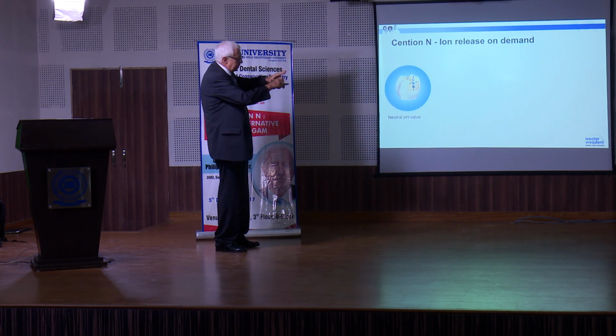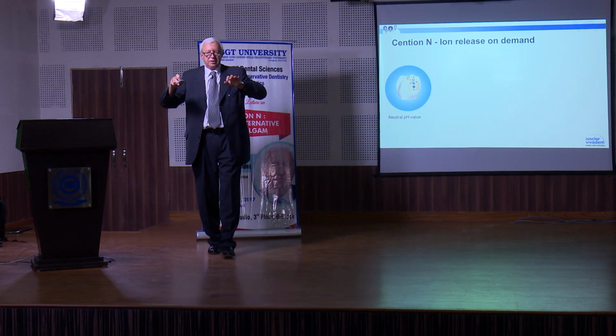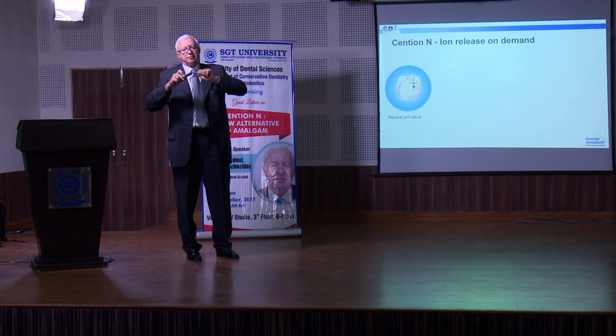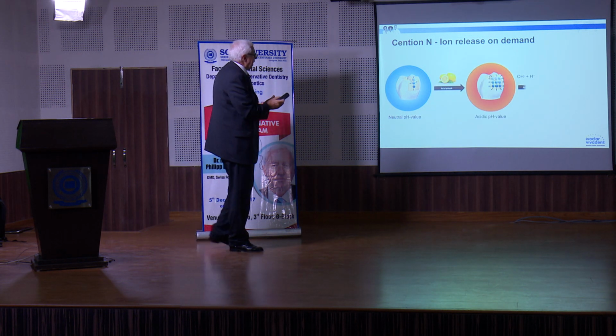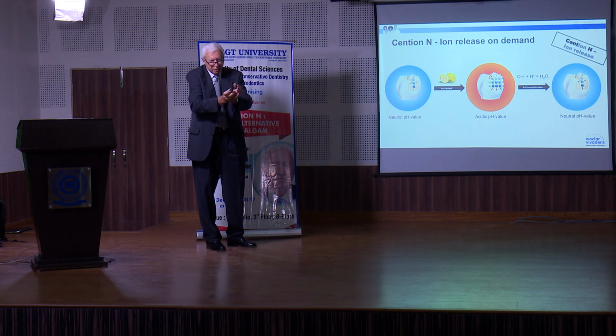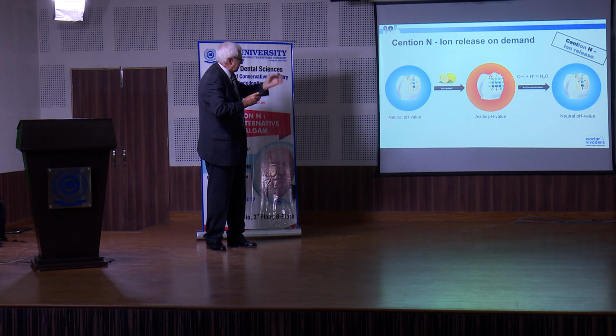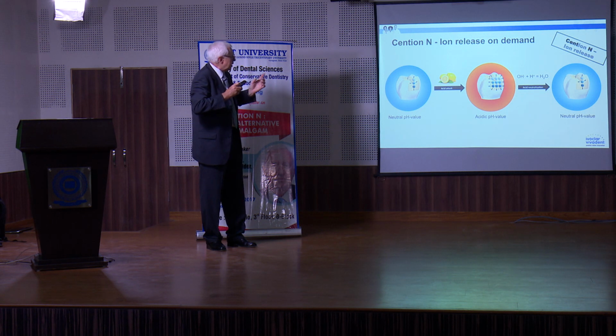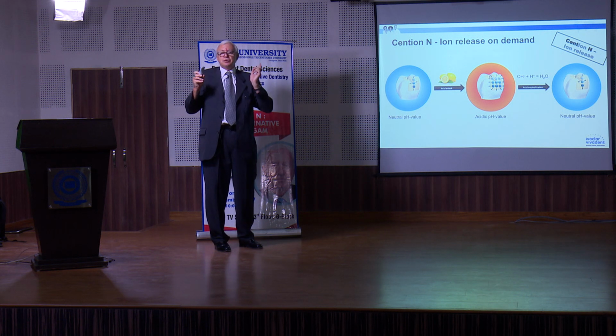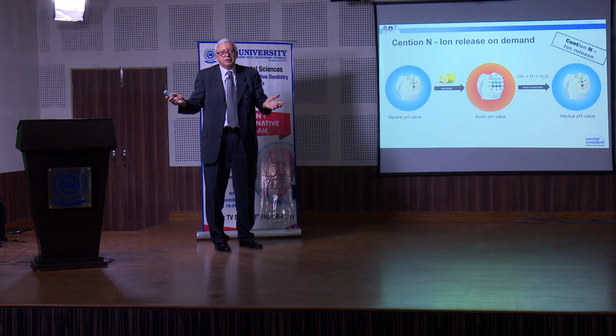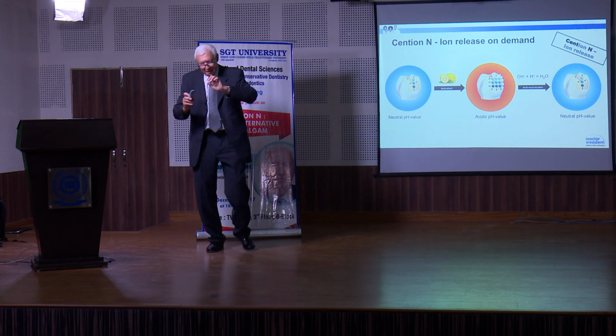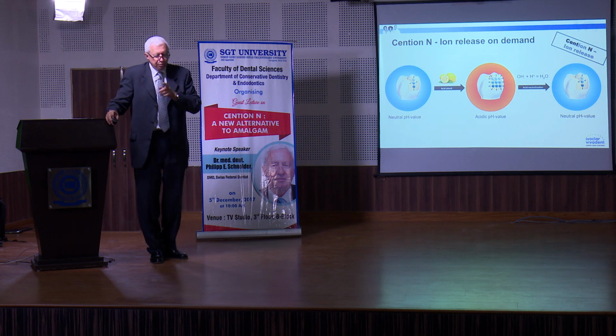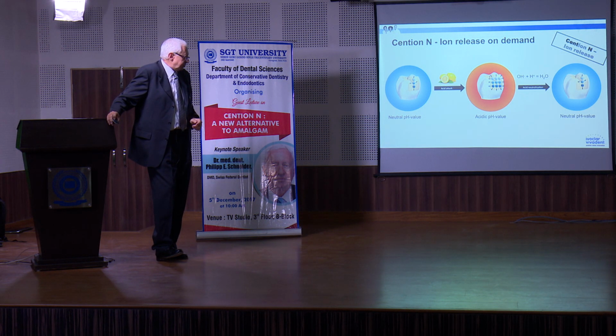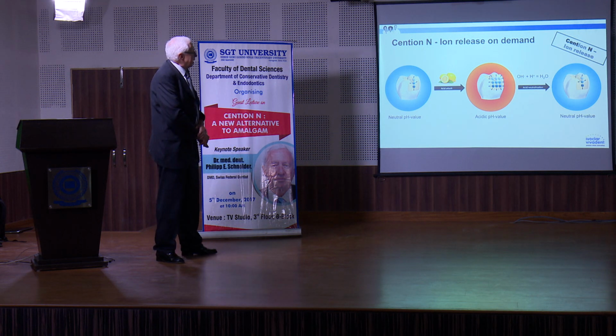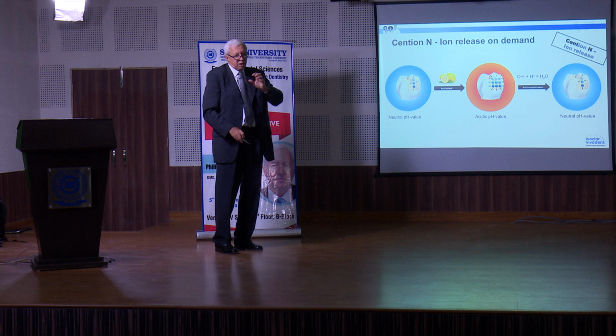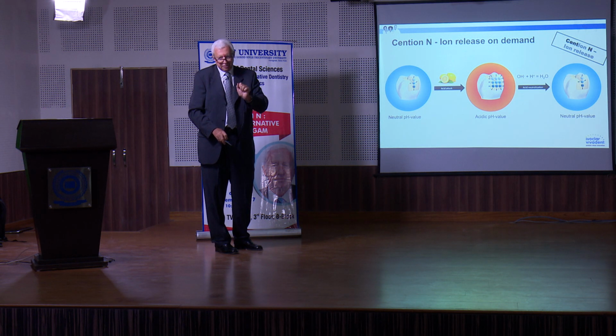Again, normally I have a neutral pH value in the oral cavity, about 6.8, around 7, okay? Then, under an acidic attack, when we have a lot of plaque biofilm, then I have more release. This is ion release on demand. You see the protons together with the hydroxide. This makes neutralization, water. It's very simple. And it is no fake. We can prove it, and I can show it later. We developed, 35 years ago at my university, a method to measure directly in the mouth of the patient the pH, calcium, fluoride. We can prove this.